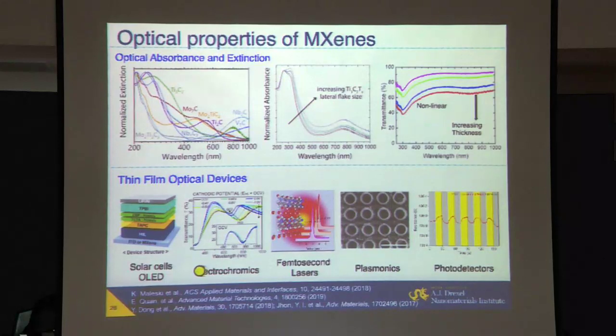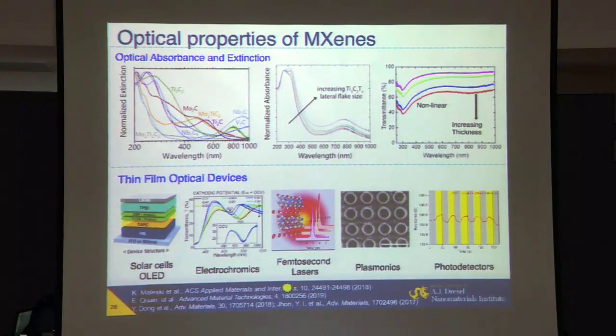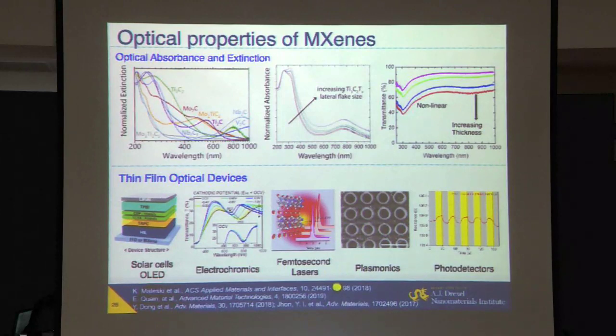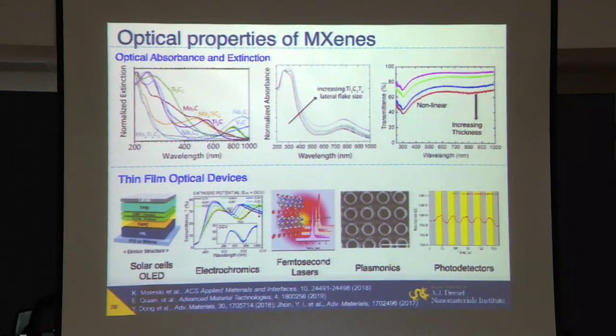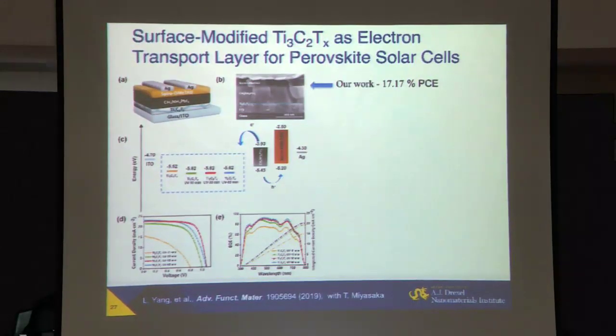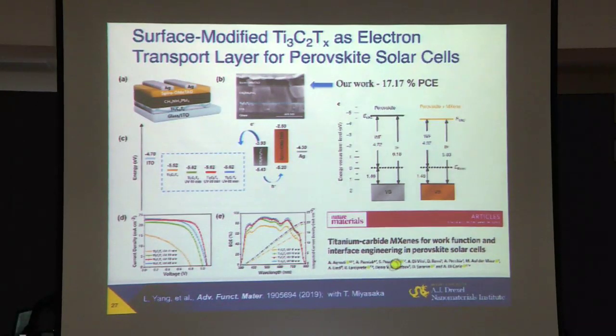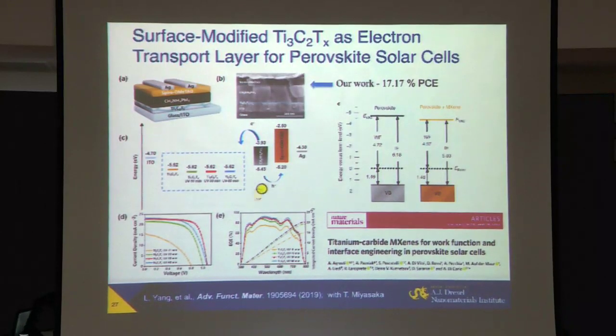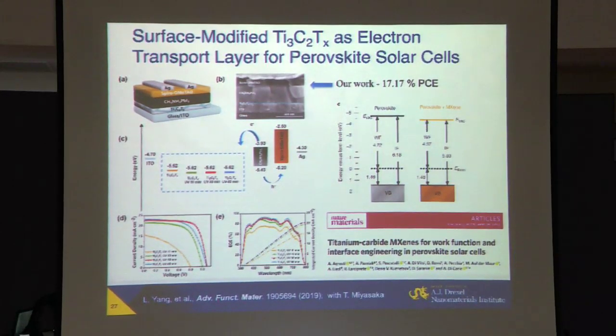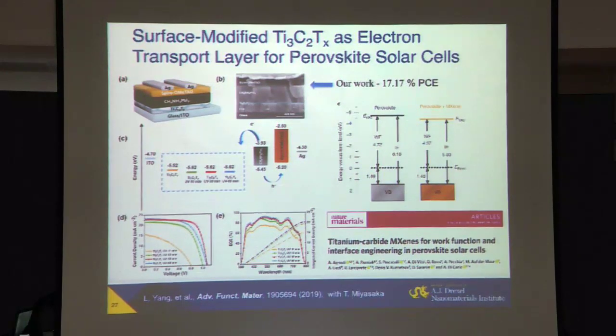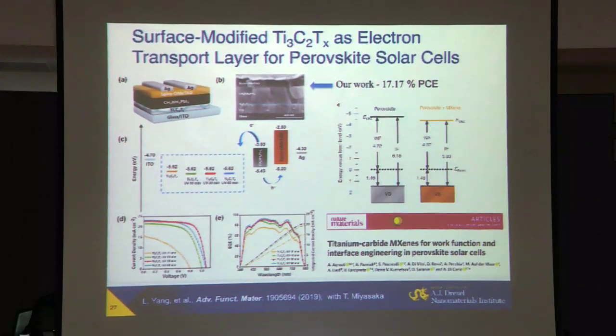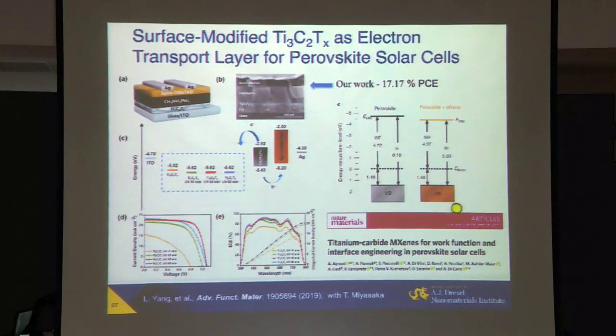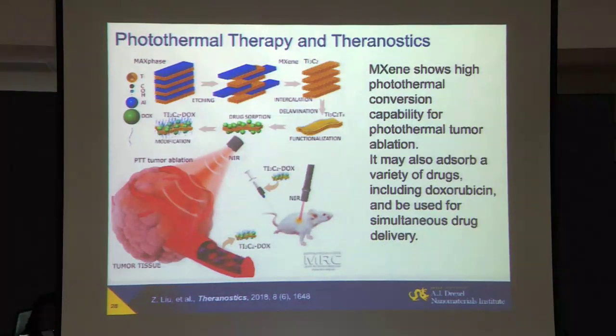And as a result, of course, they start finding applications in solar cells, OLEDs, femtosecond and random lasers, plasmonics, photodetectors, many other applications. For example, just about 2 months ago, we published a paper on using tunable work function, which again can be changed and modified by changing surface termination. And at the same time, another group from Italy and Russia, a mixed group, published another paper using exactly the same principle here. So it shows how quickly research is growing and propagating.